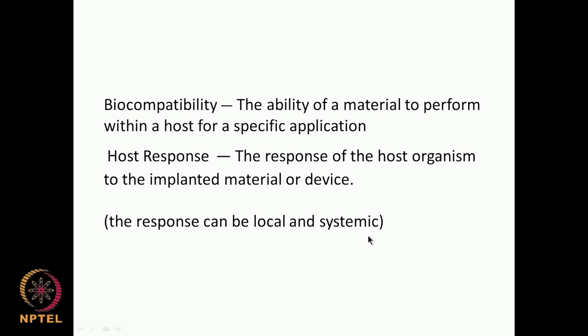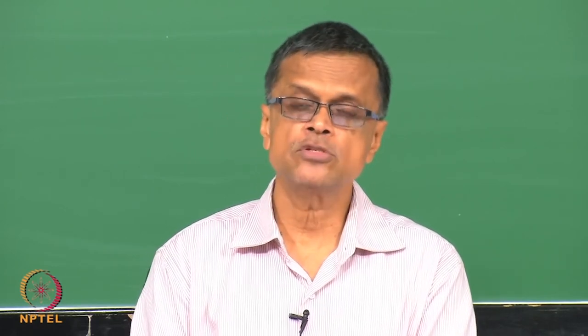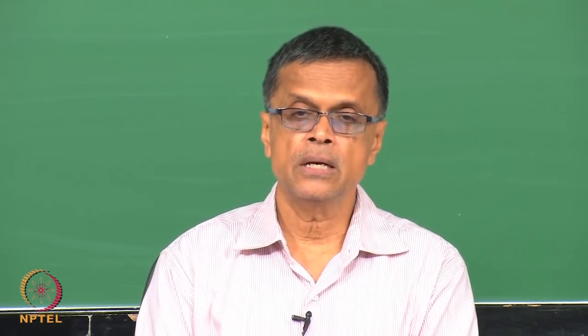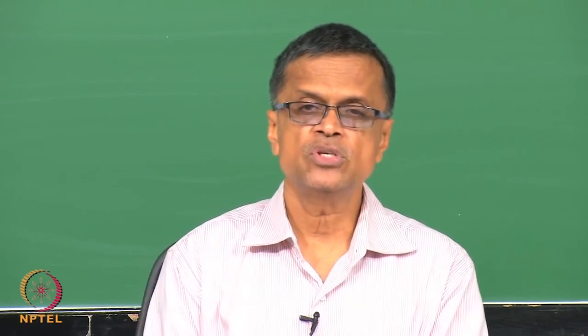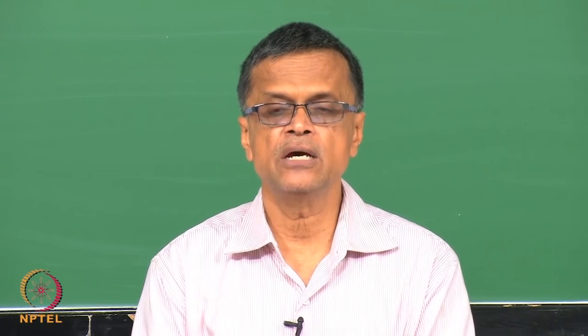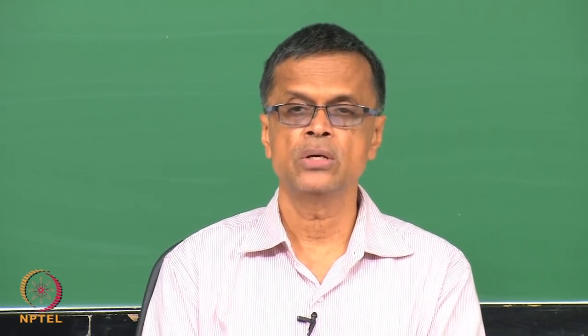The response could be local — wherever the material is placed — or it could affect the entire system. For example, poly lactic acid, an FDA-approved polymer made up of lactic acid, finds many applications inside the body. When it degrades, a little lactic acid is produced, which is slightly acidic. There could be very local acidity that may harm nearby cells, but the acidity of the entire human system will not change — only the local environment could have adverse effects on cells or tissues near where the material is placed.